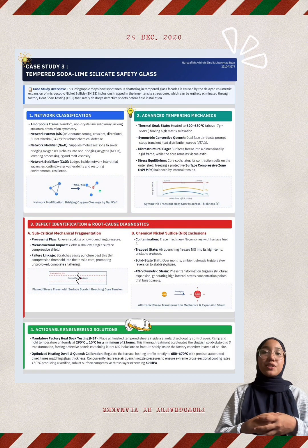But if the engineering isn't perfect, catastrophe strikes. There are two primary failure modes. First, subcritical mechanical fragmentation. If the factory quench pressure is too low, it yields a shallow, fragile, compressive shield. A simple surface scratch can easily puncture right through this thin barrier into the high-tension core, prompting unprovoked total shattering.